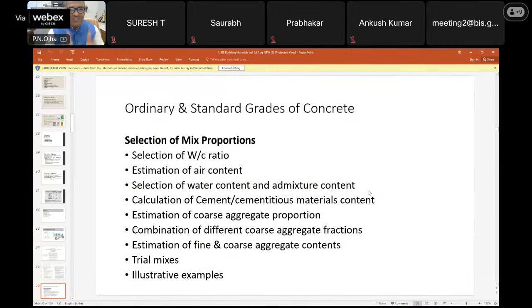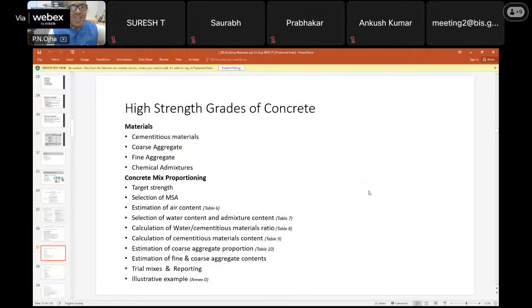Okay, so these are the steps you can go through. I have already explained: selection of water cement ratio, air content, then water content and admixture content, then cement and cementitious material, coarse aggregate proportion, then different coarse aggregate fractions, then estimation of fine and coarse aggregate, then trial mixes. Illustrative examples are also mentioned at the end of the standard guidelines. So following this, one can design the concrete mix proportion. And for high strength grades, how to select the materials and the procedure are almost the same, with a little bit of difference in the values.